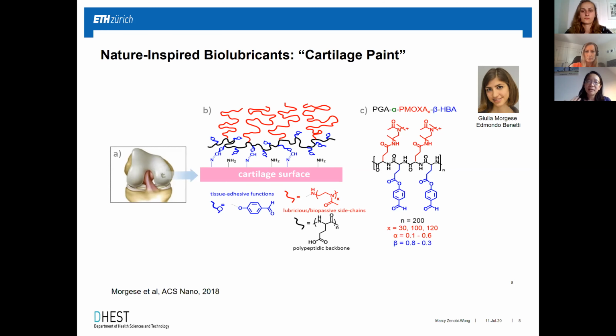And Giulia attached groups that would allow it to covalently attach to the proteins, the exposed proteins of the cartilage. But she also decorated this backbone with these red brush-like molecules. This is a synthetic polymer that is one of the polymers that is the most hydrophilic. So once you have this paint applied, these brushes form this lubricious environment on the cartilage surface.